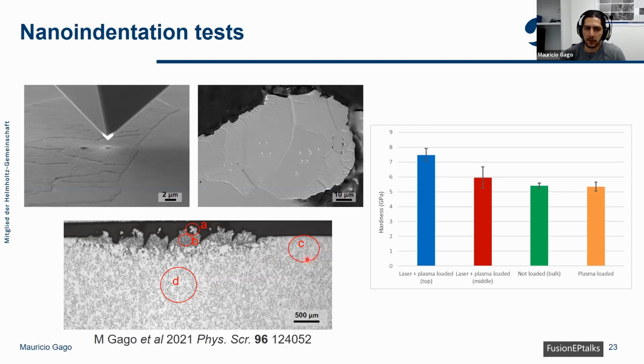And then we also tested the sample surface where only plasma affected the sample, and we can see that the hardness of the sample is the same as in the bulk sample. So the plasma by itself doesn't affect the hardness of the material. And this is important because hardness is normally connected to the brittleness of the sample. So this in part is because of the hydrogen and helium embrittlement. And yeah, this effect we can see clearly here.